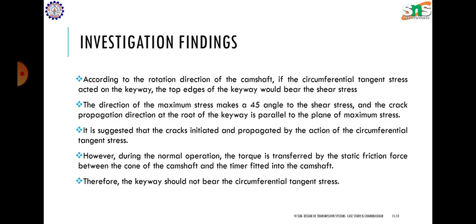Okay. However, during normal operation of the injection pump, the torque is transferred by static friction force between the cone and the timer fitted onto the camshaft. Therefore, the keyway should not bear the circumferential tangential stress. So in the normal operating condition, there is no circumferential tangential stress acting on the keyway.